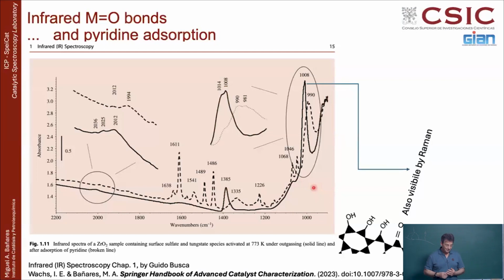Back to the infrared. Infrared will report many things, maybe not below 1000. You can see this band at 1000, for instance, okay, you can see the vanadyl or the molybdenyl group. But anything below that will be a challenge, and mainly if the loading of the oxide catalyst is low. But above that frequency, it can really report very many things. For instance, I was telling you, depending on the position of the hydroxyl, you will see whether this is more or less acidic. But you can chemisorb probe molecules. You can chemisorb CO, you can chemisorb CO2, you can chemisorb pyridine, which is a very good probe for acidic sites, Brønsted and Lewis.